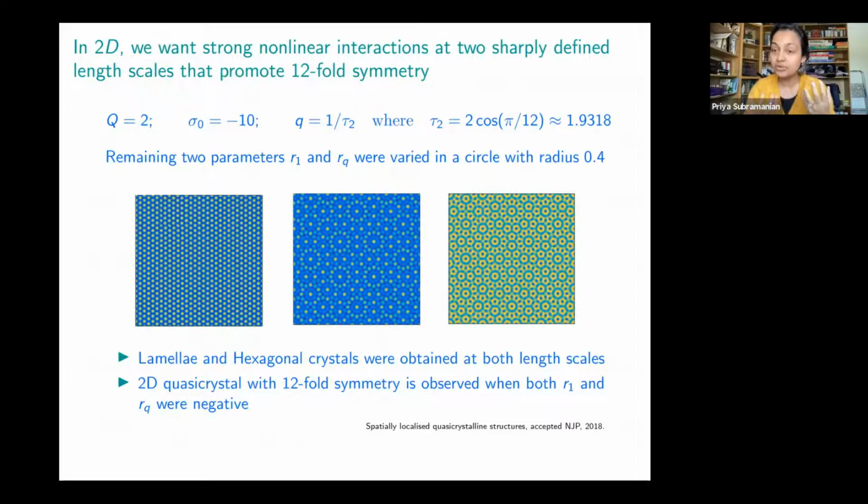And the way we can imprint that is if we go back to the slide that I want to show you. Basically, we can imprint this dodecagonal quasicrystal by asking what the angle between two adjacent wave vectors should be in my reciprocal space. And if that has a 12-fold rotation symmetry, then I'm effectively imprinting the possibility for these length scale ratios to be in the correct value for a dodecagonal quasicrystal to form.